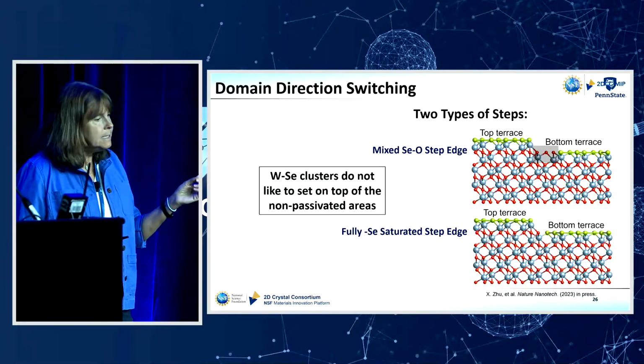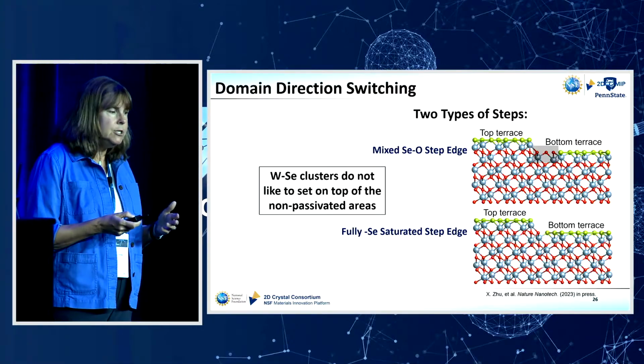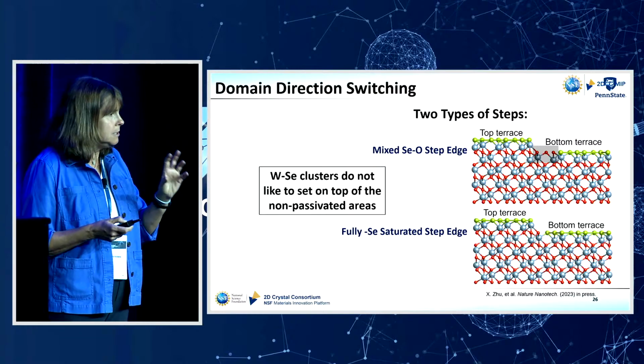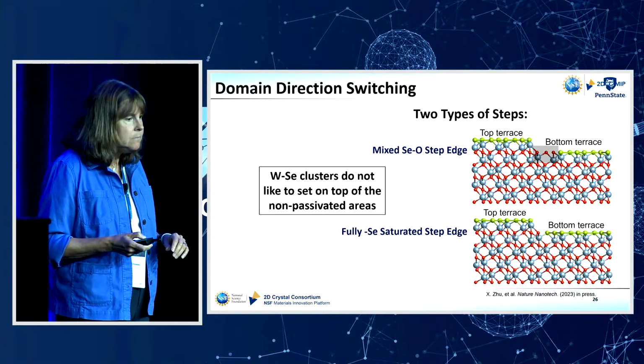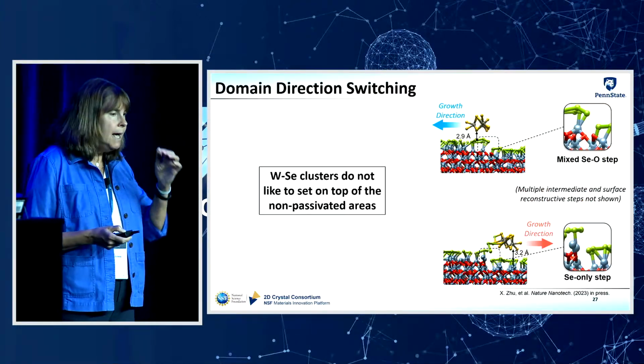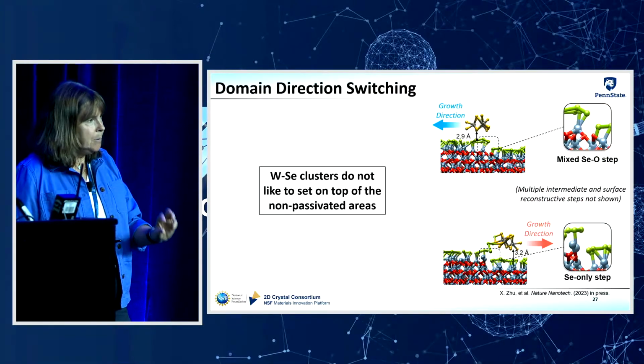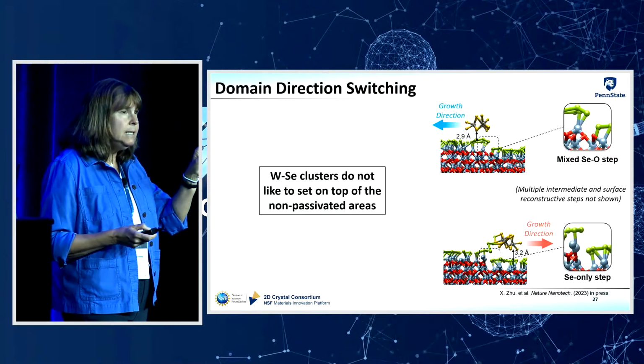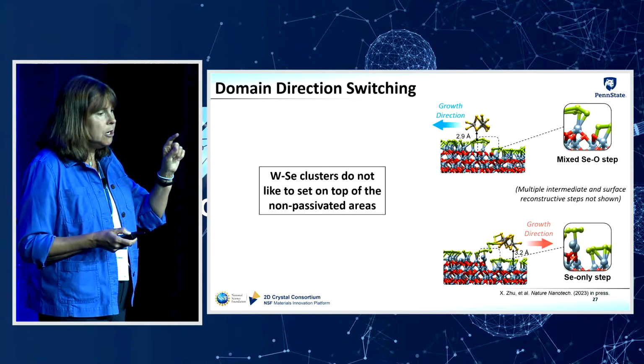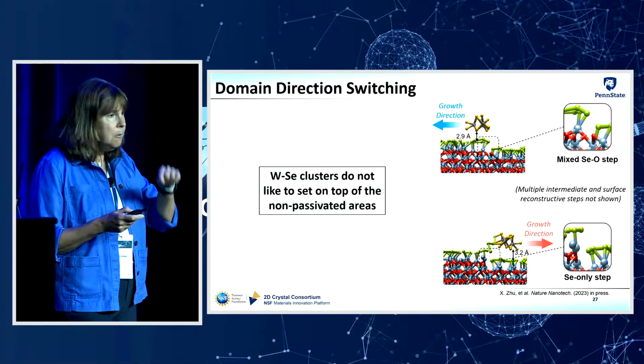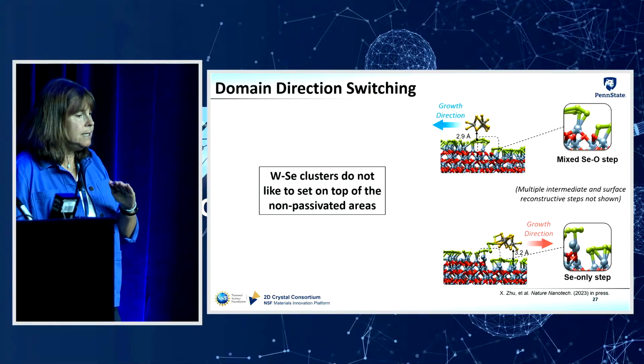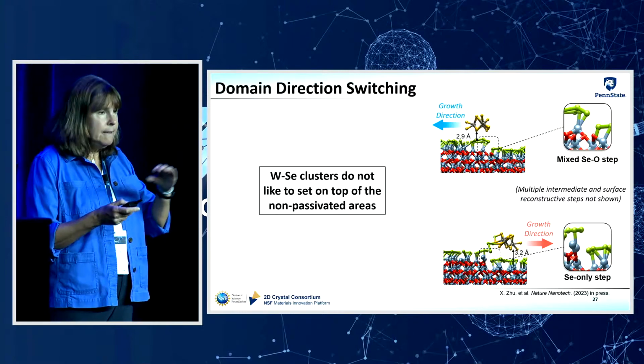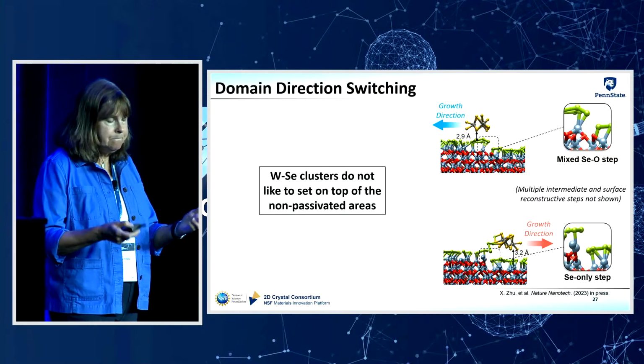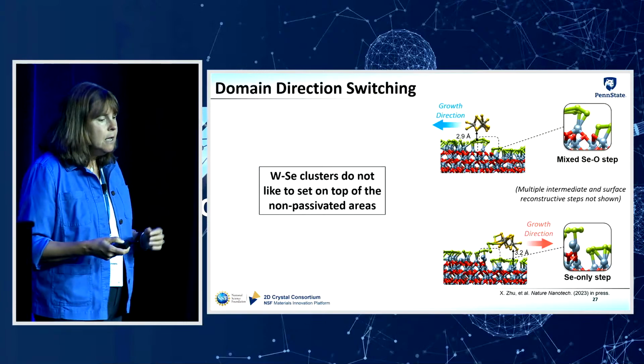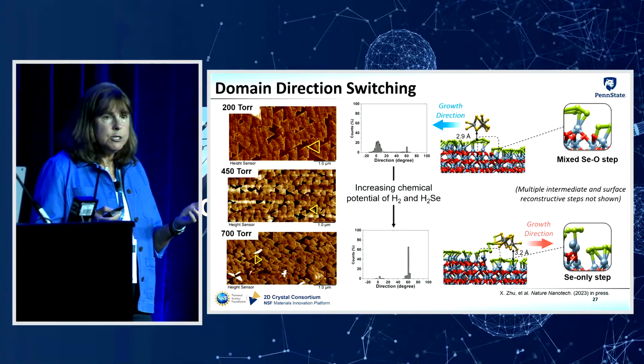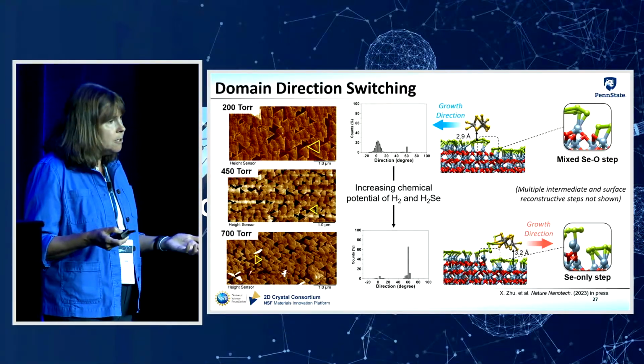And what we find is that the tungsten diselenide doesn't like to nucleate in regions where there's still some hydroxyl groups present. So as a result, when we have hydroxyl groups that are present at the bottom edge of the step, then the most likely location for nucleation to occur is the top edge of the step. However, when the sapphire surface is fully selenium passivated, then the bottom edge of the step is going to be the preferred location. So this is what the model predicts. And fortunately, the experimental results support that model.